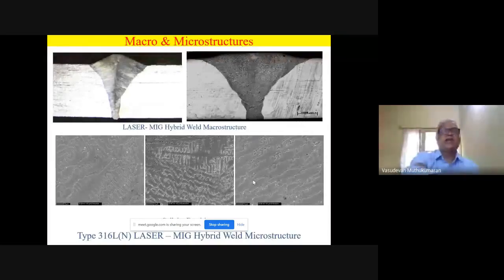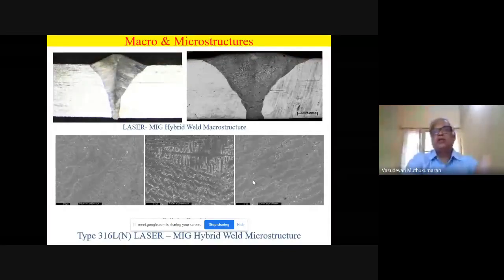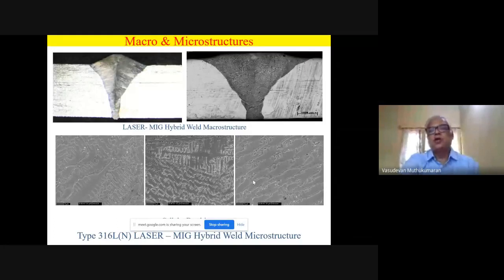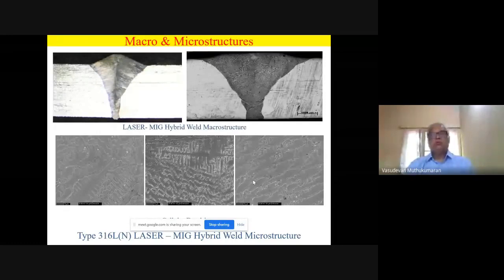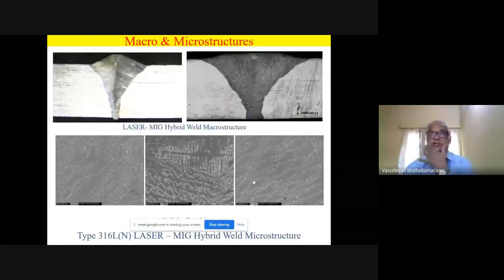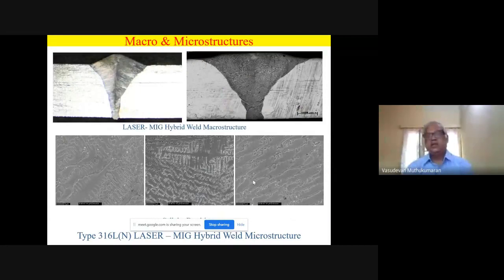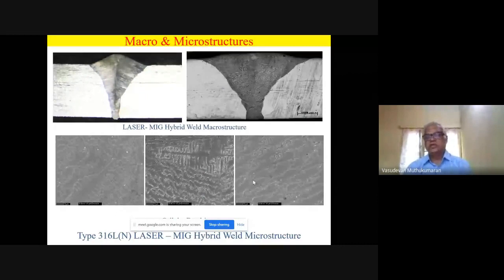You can see the triple cap reinforcement on the top, narrowing down to the root, and the microstructure also. Because we are using a filler metal here, we could get the desired microstructure. No porosity, no cracking, nothing is there in 316L(N). So defect-free joints could be fabricated again with the laser MIG welding system. So this is how we are using advanced welding processes, which are also automated. Some are integrated with a robot, like hot wire TIG welding, laser welding, laser MIG welding of our nuclear structural materials. Successful.